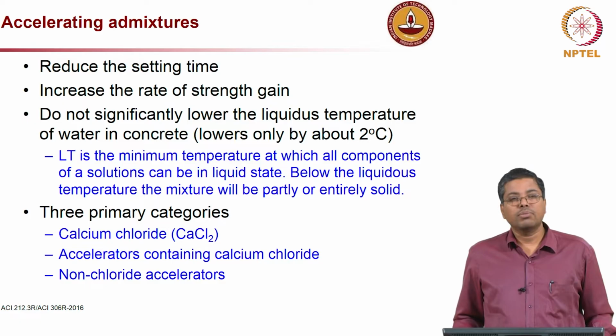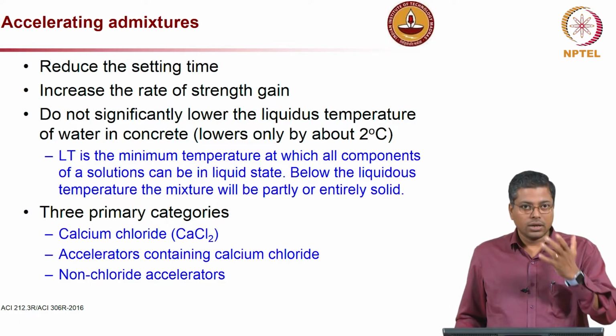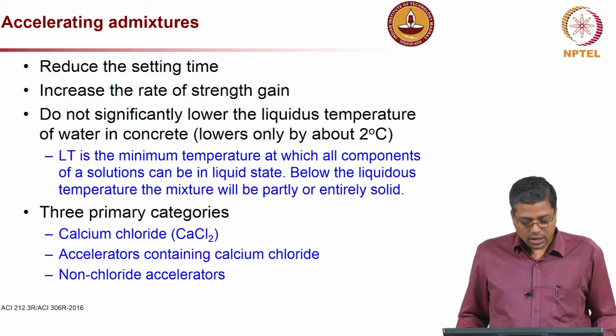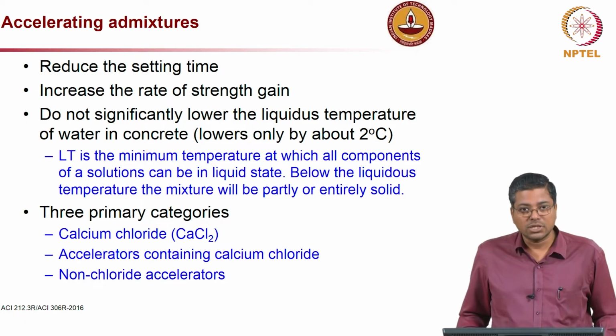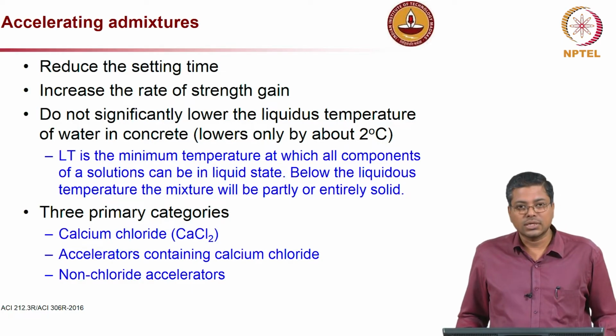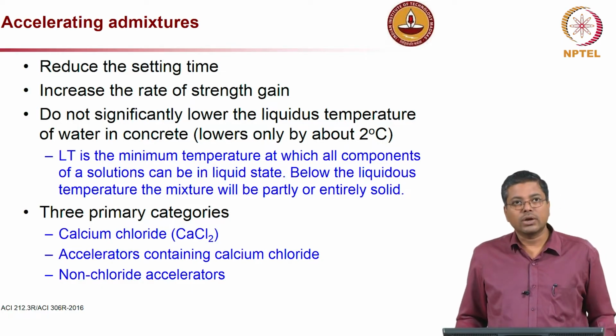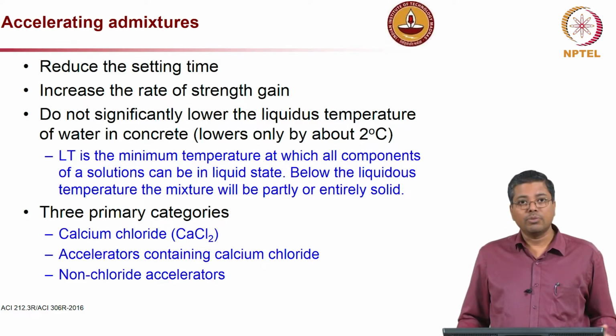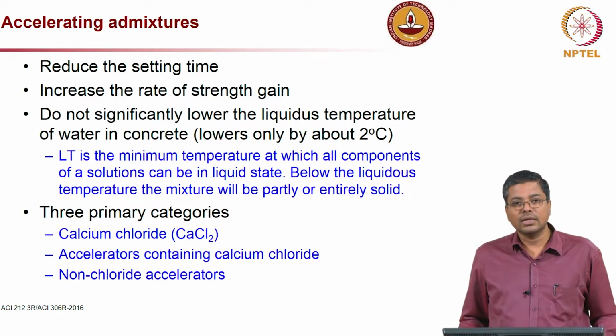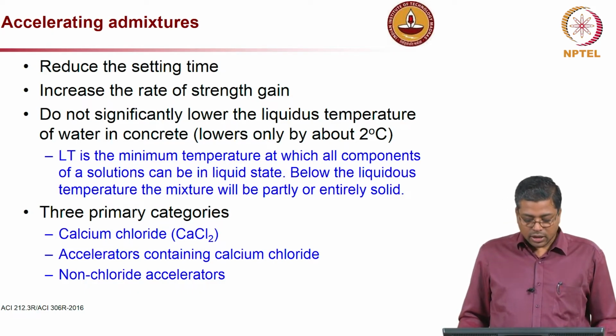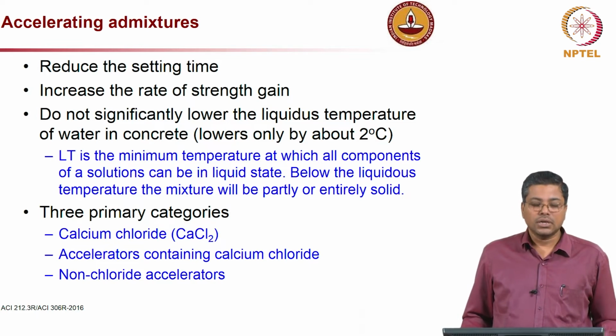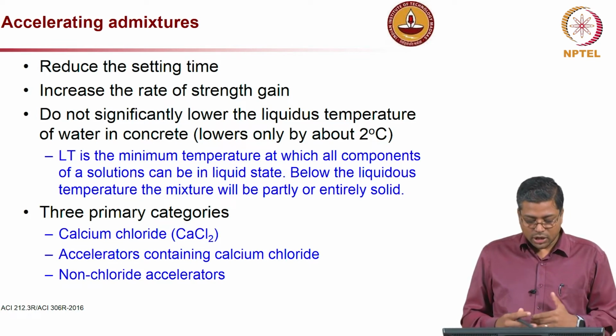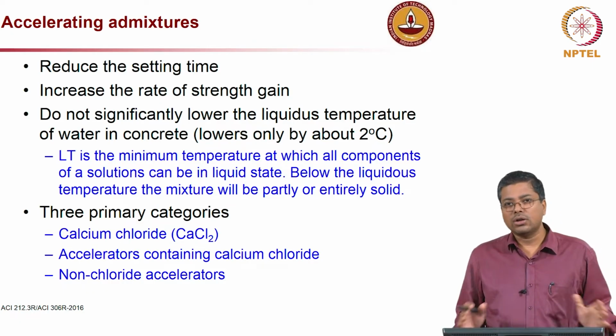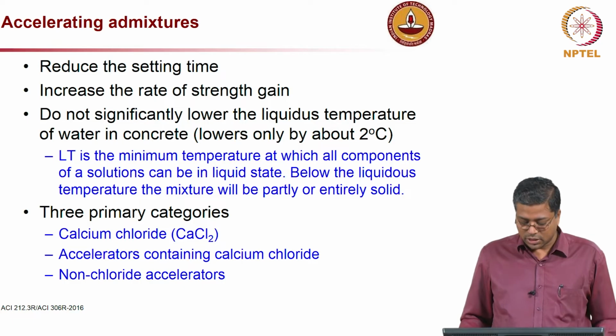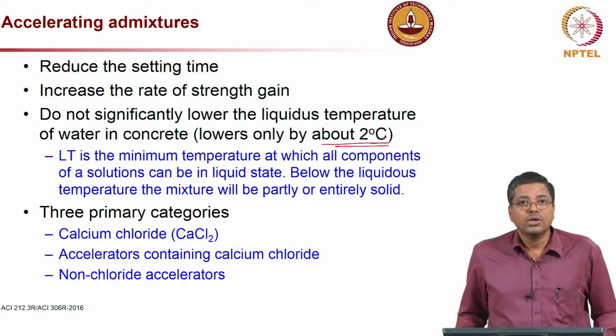Until now we were talking about the cement or the mineral admixtures, and how selection of cement can help in reducing the setting time and gaining early strength. Now let us look at accelerating admixtures, which can help in reducing the setting time and increasing the strength gain, especially at the early age. They also reduce the liquidus temperature, but not significantly, only by about 2 degrees Celsius.